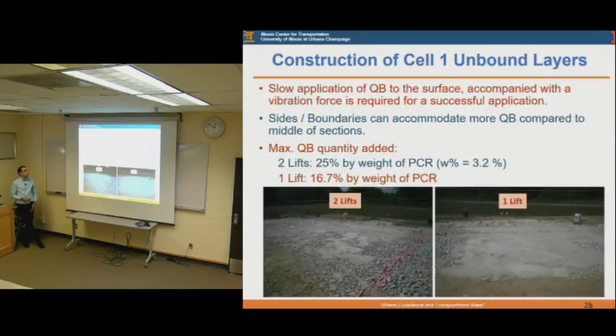So overall, for the construction of the 2 test sections with this application, we had the 2 lifts and then the 1 lift. For the 2 lifts, we were able to put the 25% by weight of the Quarry byproduct at the higher moisture content. But for the 1 lift, because the Quarry byproduct has to percolate through the 21-inch depth with this higher moisture content, we were only able to get 2/3 of that amount inside the lift, or almost 16.7% Quarry byproduct by the weight of the primary crusher run aggregates.